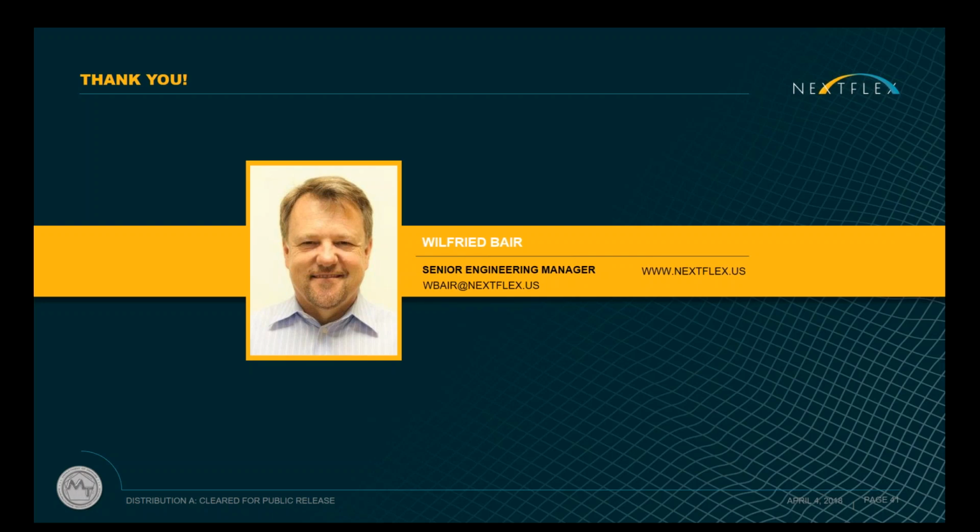Okay. Do you think screen printing will remain the standard process once it's in mass production? So we used screen printing because it gave us the desired thickness of conductive material very quickly, and we used it in combination with laser ablation to create the fine features we needed. And the process works well. We have both inkjet and, for example, gravure offset that have very high promise to be a scalable digital printing method, but it takes work to achieve the thicknesses we need for the conductive materials.